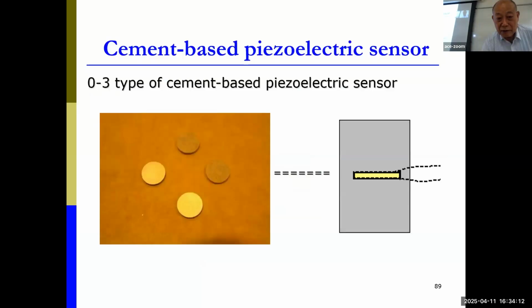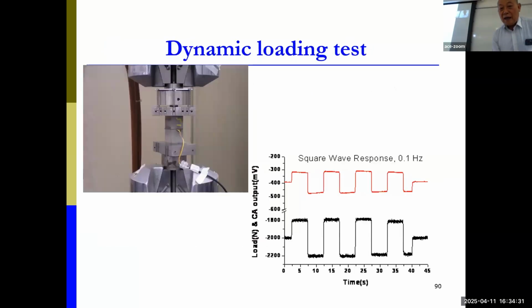Then we have the cement-based material. This is work we also developed at HKU for many years. Basically, we use powder from piezoelectric material mixed with the cement, with some guidance for the fit, and then we produce this transducer. You can see it follows the force very well. On the top, the red one is the force applied by the MTS, and the bottom black one is the signal output of the transducer.